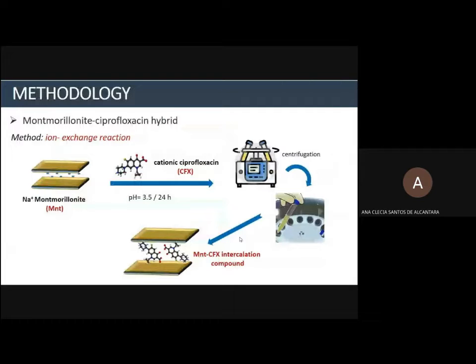In the methodology used to obtain the montmorillonite ciprofloxacin hybrids, the method was an ion exchange reaction, where to the suspension of sodium montmorillonite is added a solution of cationic ciprofloxacin prepared in pure water, at a pH of 3.5 for 1 day. After that, the suspension is centrifuged and the solid is isolated, obtaining the montmorillonite ciprofloxacin intercalation compound.